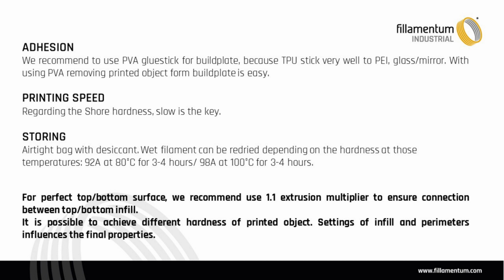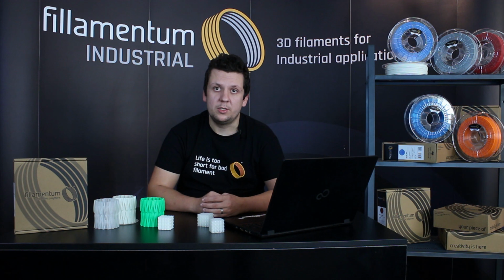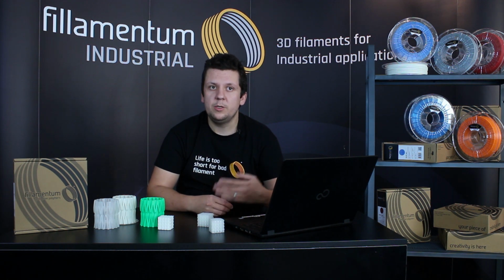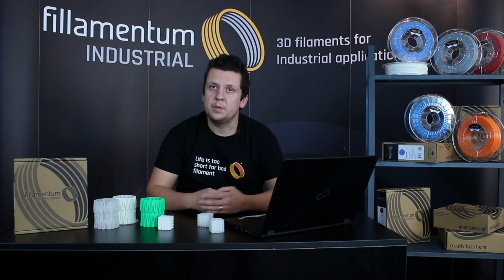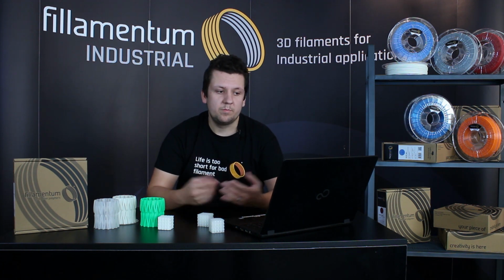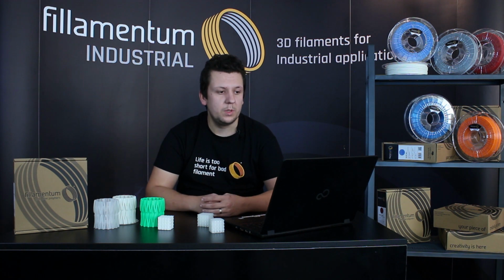Another important thing about the TPU is the hygroscopy of the material. So you need to store the material in the right condition, because if you leave the material in open space, in the room, the filaments become wet and you will see a huge effect on the printed part. You will see oozing, stringing, jamming, the layers will separate very easily, and so on. So please store the material in proper condition in an airtight bag with desiccants, and it really helps you with the perfect prints.